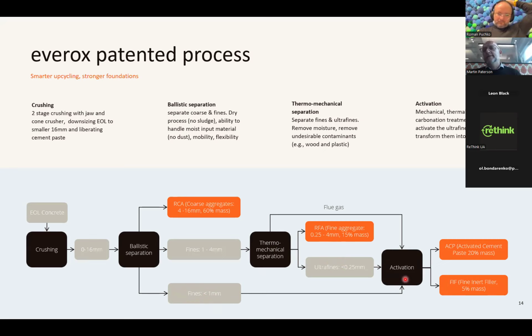And again, Leon also introduced some different options to activate it. What we are doing is we start with a selective grinding process, so mechanical treatment, where we only grind the amorphous content. Leon also said there's still a lot of silica in that, depending on where you are in the world, depending on the nature of the concrete waste, more or less. Here in the Netherlands, we see up to 40% silica in that fines. So we only want to grind the non-aggregate part, and that's what we do by selective grinding.